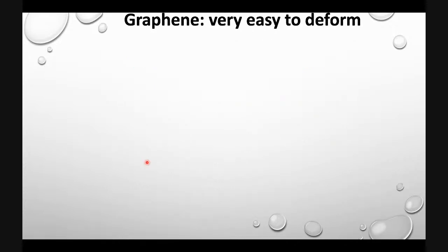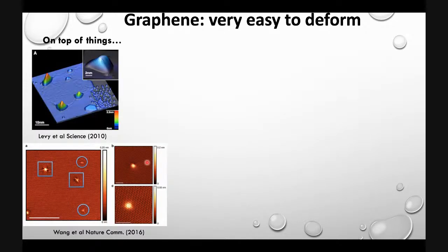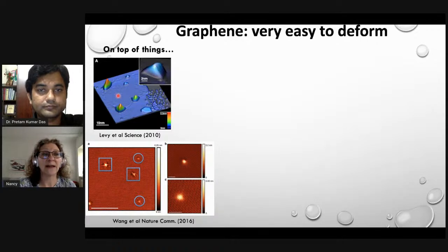So, the interaction that I am going to talk about today is produced by deformations. And we know that being a two-dimensional membrane, graphene is a very easy material to deform. From the very first experiments where they deposited graphene on platinum, they found that after deposition, there were regions where the graphene was sitting on top of little bubbles or mountains. And the bubbles have a very peculiar shape of triangular mountains and have different characteristics from the properties that were measured in the flat regions.